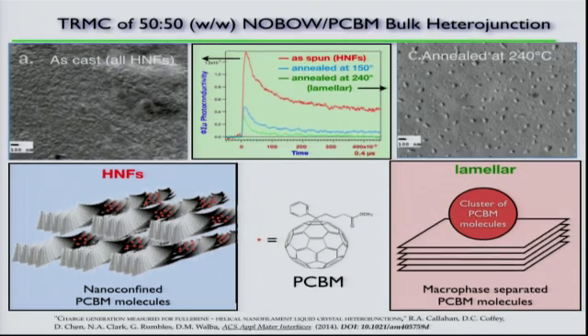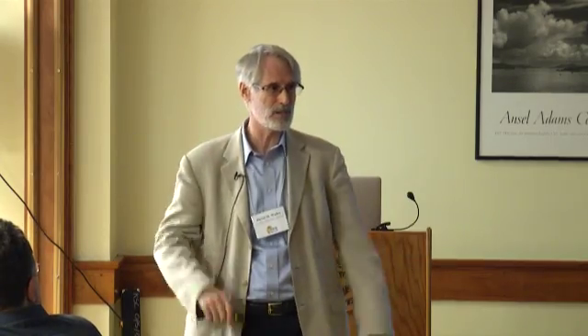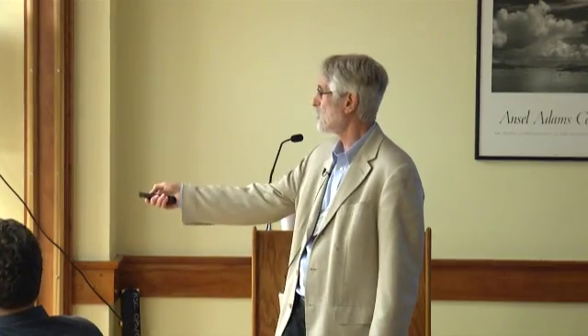Okay? If you anneal it, the idea was we would anneal it, improve the morphology, cool back down, and get something that was better. And what happens instead is the signal totally disappears. No signal. So what's up with that? When you do the TEM on the substrate, what you find is you have helical nanofilaments before the annealing. When you anneal, the surface kind of makes the layers go flat. You melt it and cool it back down. You're in a very, very thin film. The layers go flat, and that expels the PCBM.